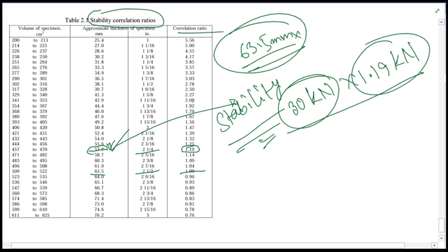And from this chart, although I do not want to discuss these basic properties, as you can see, as much as the height is decreasing, the correction factor is increasing. That will result in a higher stability than the obtained one, just because of what? As you are getting less height than usual, it will obviously give a lesser resistance value.